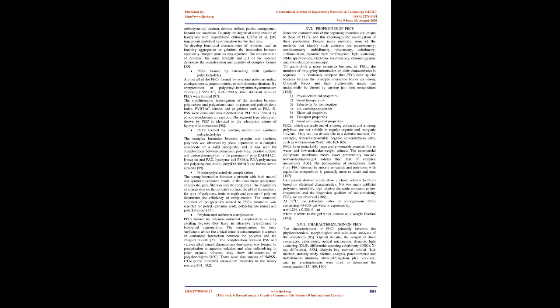Using this technique, consecutive layers of oppositely charged polymers are deposited onto a solid substrate, for example, silica particles. 65, sodium poly(styrene sulfonate)/poly(allylamine hydrochloride)/poly(diallyldimethylammonium chloride). 66. The multi-layers are subsequently stabilized by the electrostatic interactions present in the PEC.